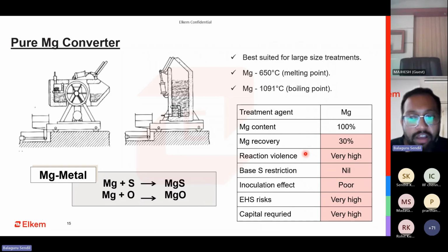More, if you want to have 0.045 amount of residual Mg, the amount of pure magnesium you have to add is extremely on the higher side. And it also completely kills your base metal in terms of having any inoculating effect. You need to add a lot of inoculants after that to make sure that whatever nucleating site this pure magnesium has used comes out as a useful nodule. Again, the EHS environment risk is quite high because it is very high and volatile. It can blast anytime if there is some maintenance issue that has been overlooked.